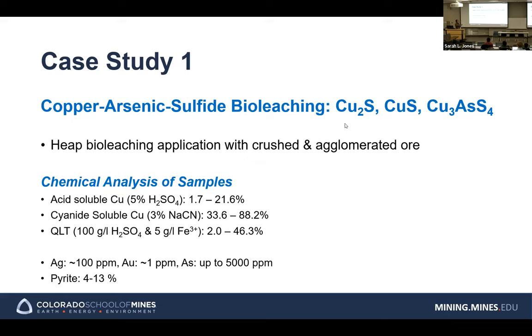And a quick leach test using high concentration of acid. This gives us sort of a thumbs up value of how much copper we can get out of the heap leaching. So that's a characterization. As you can see, it's not easy to extract the copper using sulfuric acid. And there is a little silver and just about 1 ppm gold in there.